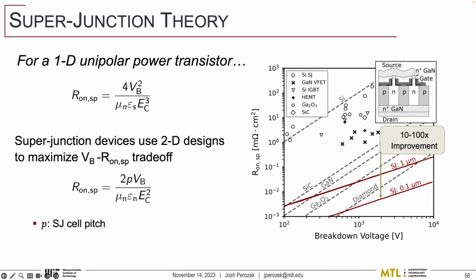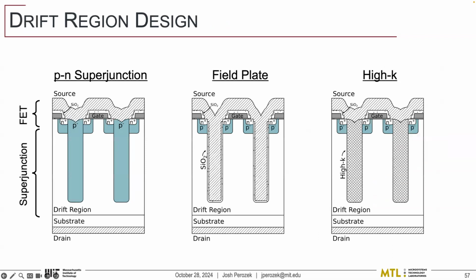This has been used in silicon. On this plot, I have a whole bunch of different random data points from various devices you can buy. And you'll see a lot of silicon ones are actually past that line, and they use exactly this structure here to make that happen. There are three approaches that people have been able to figure out to make this happen in silicon. There's the PN junction, or PN superjunction. There's a field-plated drift region, and there is a high-K dielectric drift region.